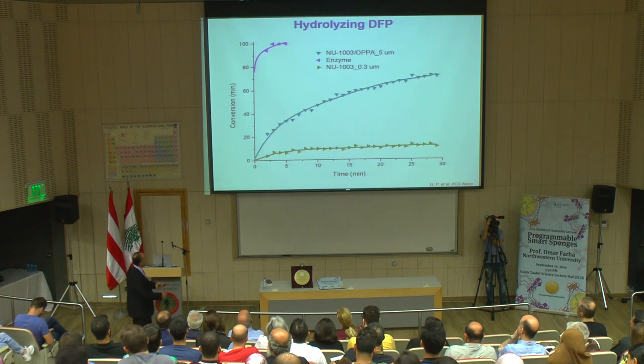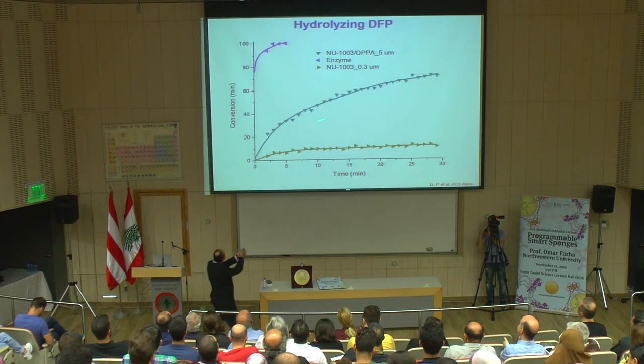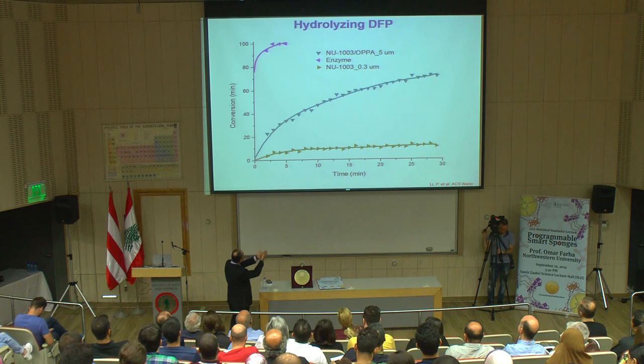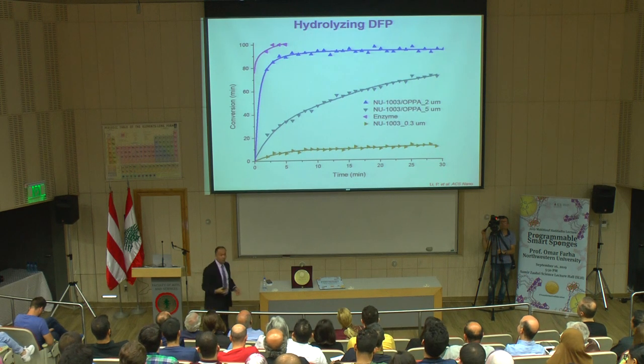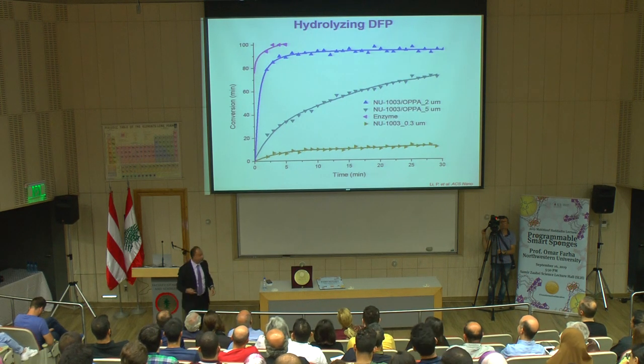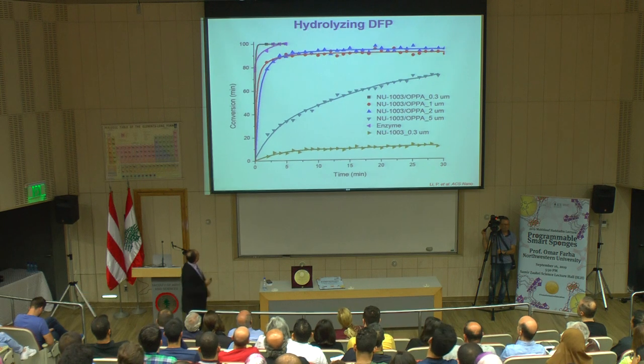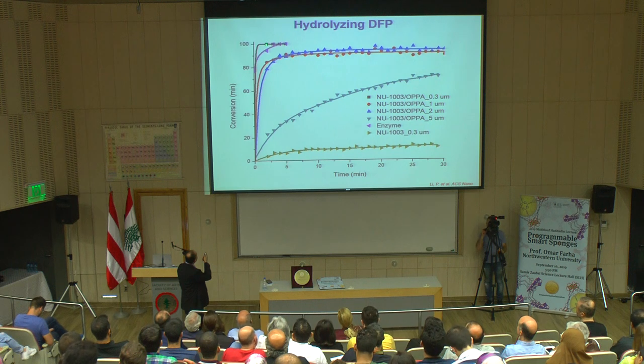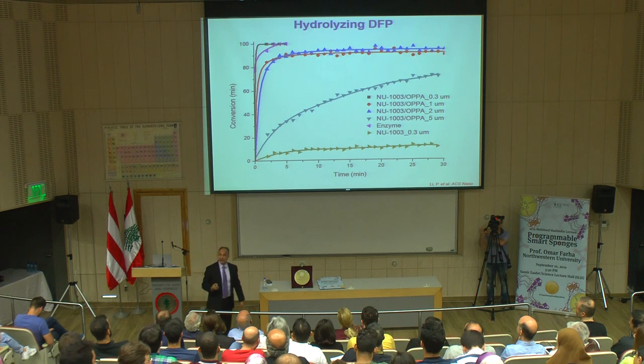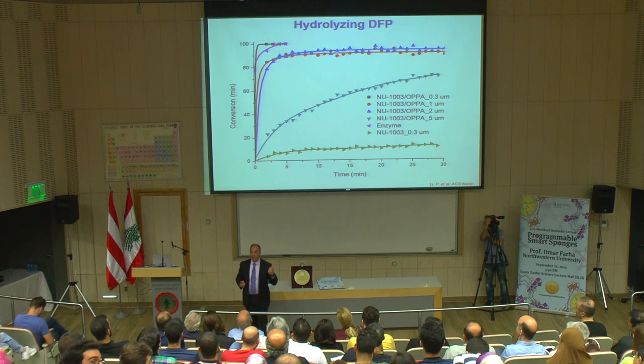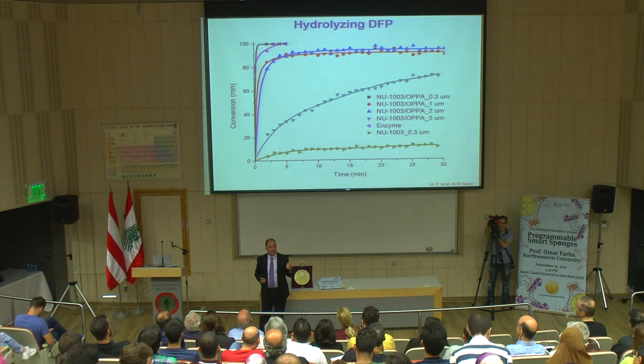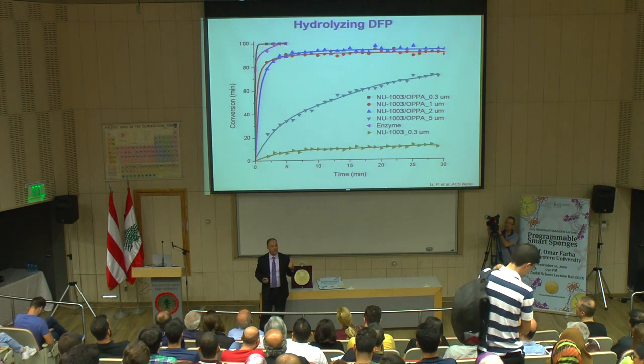So we went and we tested our material. If you have large 5 micron, you could see we saw something similar. You make your material smaller, it gets better, smaller still. When we go to the nano regime, we see that our first point is complete by the time we take the NMR. When my postdoc showed me this result, I actually told him he did something wrong.